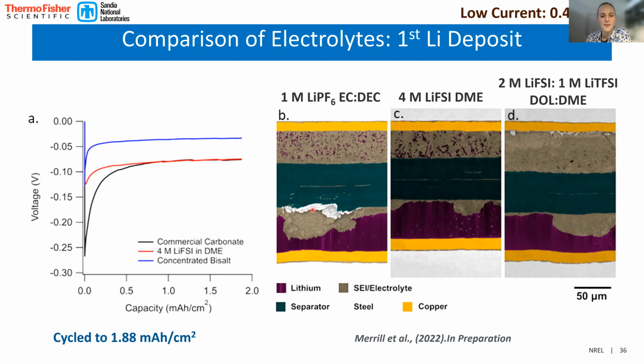This is indicative of a gas bubble that has formed on the counter electrode, because this silver material here is actually the steel that redeposited, and so that's showing a gap that formed in the structure, and then where we were imaging that there was a big hole there, and that's why the steel filled it in.